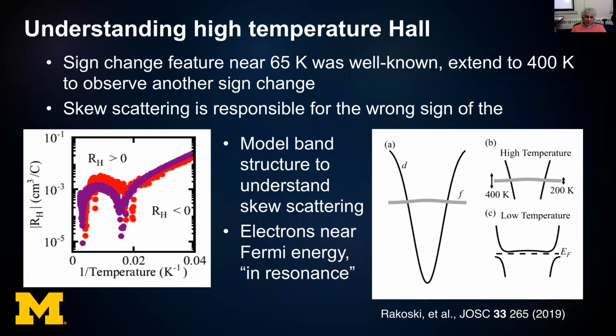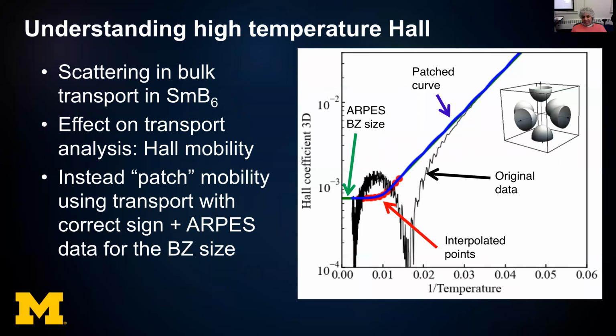Now, I just want to briefly mention the Hall experiments. We have extended these to 400 Kelvin. We were expecting to see less of this resonance scattering, because if the thermal broadening, kBT, gets bigger than the broadening of the f bands, then we expected to see electron-like behavior again, and we have observed that. Now, in order to analyze the Hall effect, you cannot use the Hall coefficient at high temperatures.